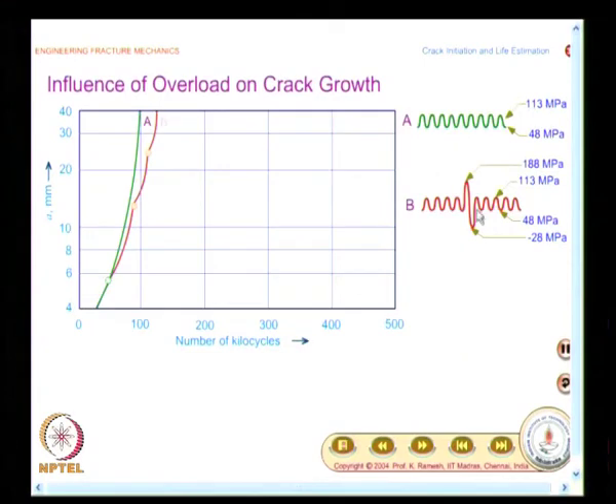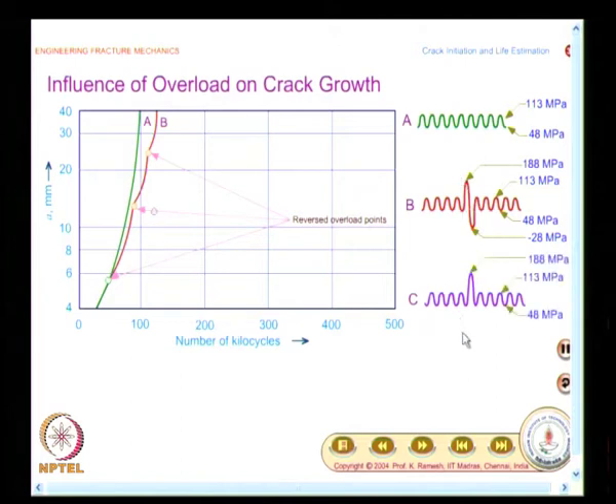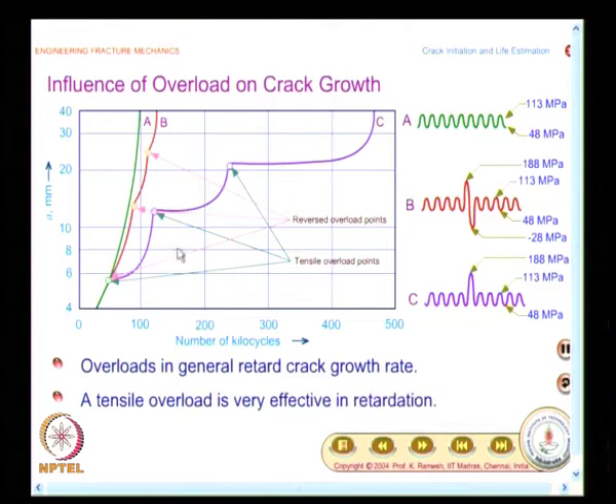And we have looked at two different kinds. In one case, you have a load reversal. In another case, you have overload only in the positive direction. And what this graph showed was, when you have overload only in one direction, the retardation effect is very significant. Whereas, if I have a reversal of load, the retardation is present, but it is not that effective compared to the original crack growth.